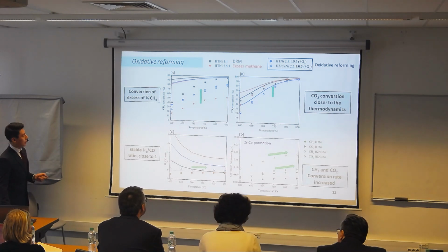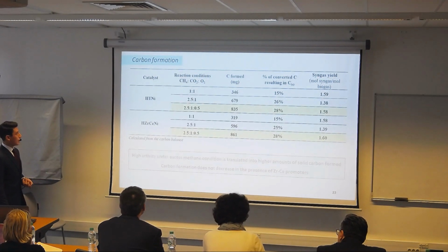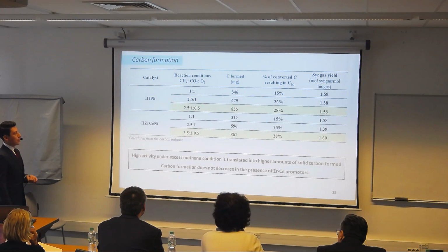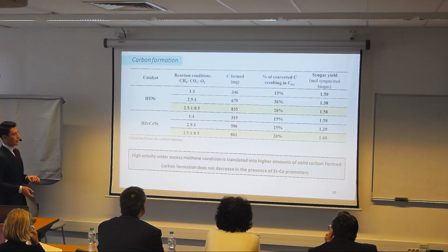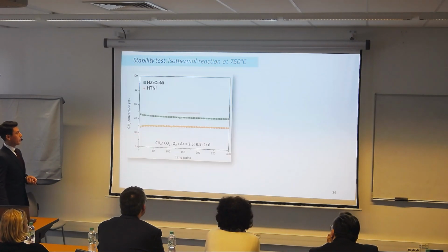and also the oxygen. About the carbon formation, we find that as the catalyst is active, we also have higher carbon formation in the sample.